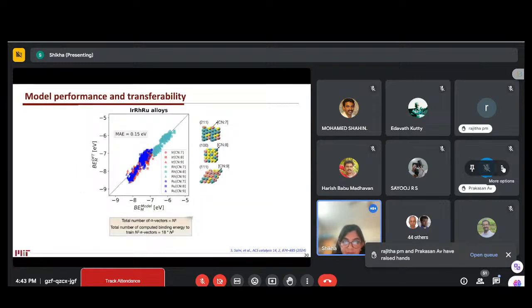Now we need to check the performance of our model, how well it can describe the different cases. We did testing on a lot of data sets. Here I'm showing only one case, iridium-ruthenium. We designed different surfaces: 111, 100, 211, and also nanoparticles. I created a lot of random configurations and calculated the binding energy from DFT and from the model. Here we see the binding energy calculated from DFT and predicted from the model. The mean absolute error of our prediction is 0.15, which is a reasonable accuracy we could have from our model.